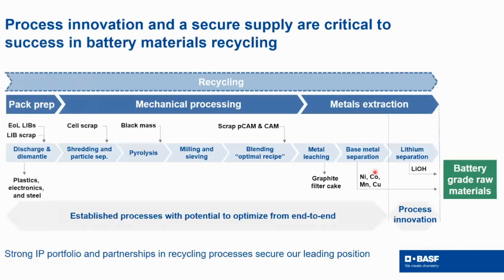And here is the value chain. We are setting up for that, are set already. We start with discharging and dismantling. And in that process, the first 50%, there's a high recycling rate already. The next part is a mechanical process. It starts with shredding, pyrolysis, and milling and sieving. And what is the intermediate here? It is the so-called black mass. At that stage, there's a good opportunity to also feed in scrap, pCAM and CAM material. And this mixture goes then into the metal extraction where nickel, cobalt, manganese, copper, and lithium are taken out of the mixture.